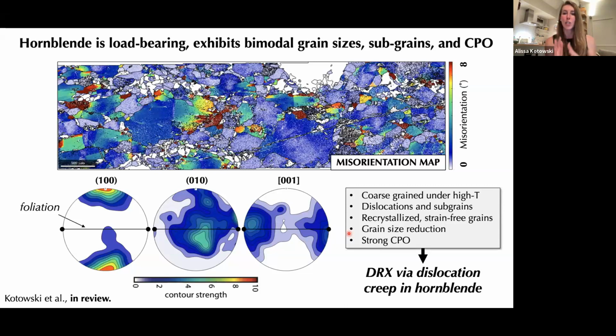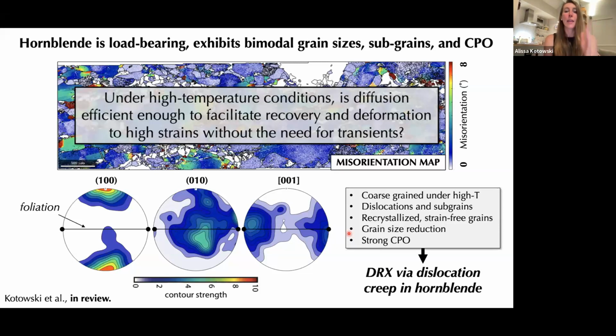So why does that matter? Why is that important in this scenario? This is important, I think, because maybe during dislocation creep in hornblende under high temperature conditions at about 800 degrees Celsius, the fact that we actually are seeing this rock properly creeping means that we have a balance between the number of dislocations coming in and the number of dislocations going out. That's fundamental to the concept of creep in this case.